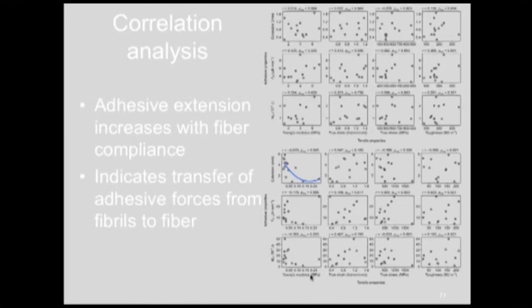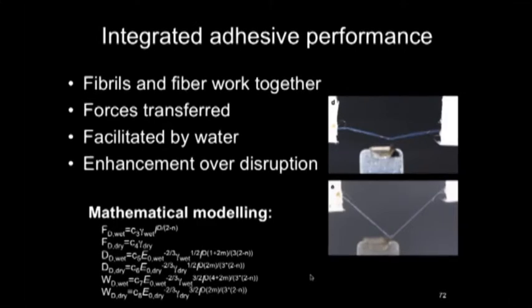This would be facilitated by water and enhanced rather than disrupted, much like I had said before with the synthetic materials. This is something that doesn't generally happen. And this also allows for an interesting phenomenon where the forces aren't just located at the attachment site, but are actually being distributed throughout the entirety of the material. So generally speaking, in most cases, adhesion is only really important in the location where it's attached. But here, as we can see clearly right before the point of attachment, the forces that are generated to resist detachment are being distributed throughout the entirety, even the parts that aren't attached, which is something that is quite unique and helpful when you're trying to capture struggling prey.